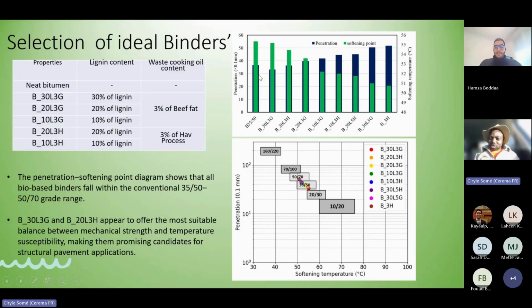In general, we have this type of evolution. When the needle penetration increases, the softening temperature decreases. On the left, we have a classical bitumen. It's the pure bitumen coming from the Eurobitume company who provide this bitumen, and the other ones are the combinations of bitumen, lignin, and two types of oil here.